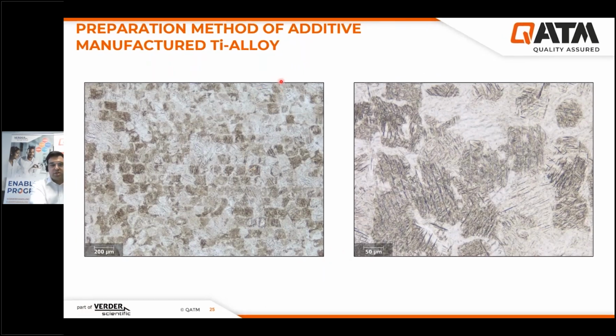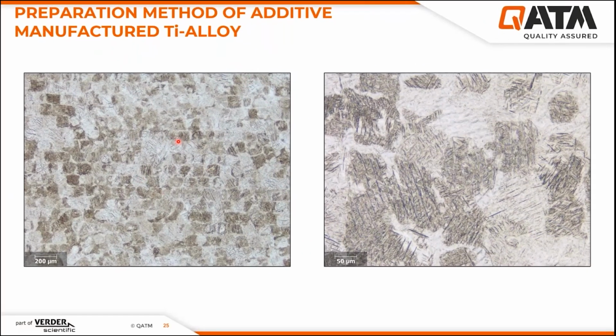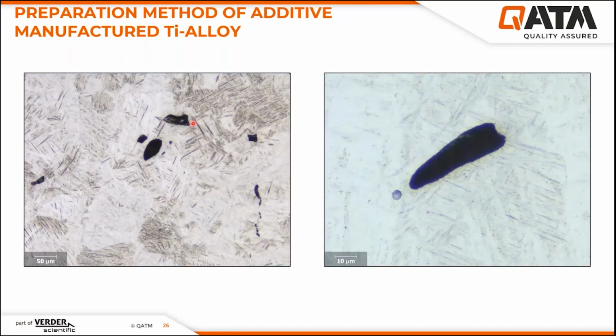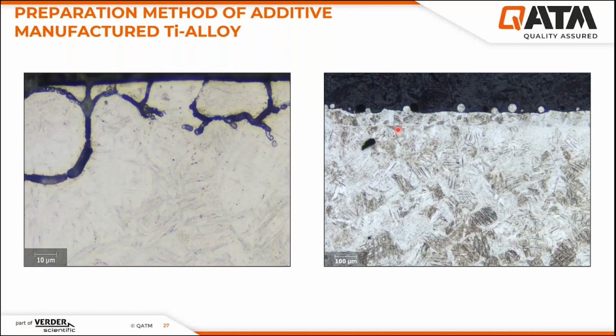Here is the microstructure of titanium alloy under the optical microscope, under lower magnification on the left-hand side and higher magnification on the right-hand side. Also, we can see some defects here, something like lack of fusion or some pores that we can see on the lower and on the right-hand side at the higher magnification.